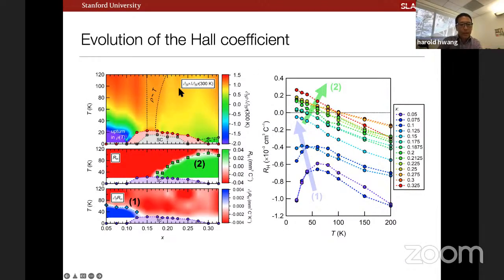Now, if we look at the Hall channel, this is the same phase diagram I showed you previously in terms of the slope, or the derivative, of the resistivity. If we look at the Hall coefficient, let me just show you the raw data here first. I want to plot two features of interest. One is this local maximum of the Hall coefficient in the underdoped regime. This tracks the resistivity upturn I told you about. If we take that local maximum, this gives you this line of points here. And the second feature is the sign change in the Hall coefficient, this zero crossing across the series. These are the green squares across the top.